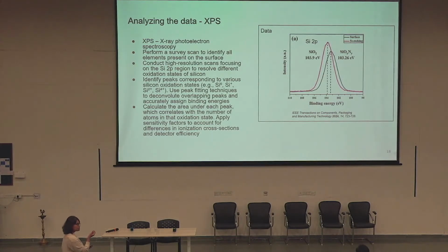This is because there is a charge transfer between the silicon and nitrogen, because of which the binding energy of the core electrons is going to change. And this change in the binding energy can tell me successfully whether there is a bond between the silicon and nitrogen, which is something that cannot be obtained using other techniques such as the EDX.